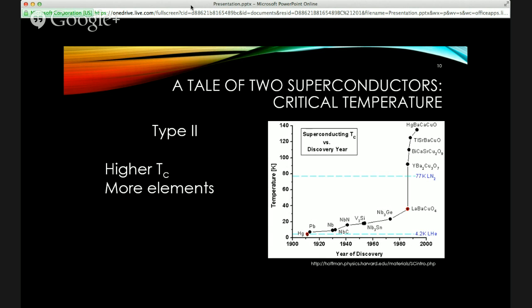So moving to type 2. So if you can see around 1911 when superconductors were first found, so at 4.2K is where you have liquid helium, which is what is used to cool around those ranges. But also you move to type 2 superconductors, which have a higher TC. And type 2 superconductors tend to have more elements. So moving on you see the niobium nitride, vanadium silicide, and so forth and moving forward. In order for technical applications and things of that nature, you use type 2 superconductors. No one really uses a type 1 superconductor. That was just kind of the starting point.